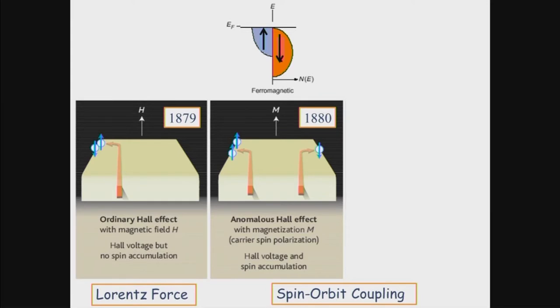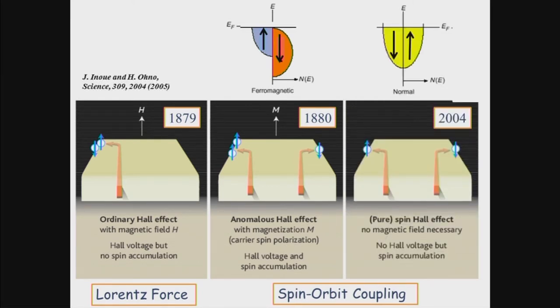And this is the anomalous Hall effect, not really useful as far as I know, but at least in the magnetism community or spintronics community, people believe the spin Hall effect might be useful. The spin Hall effect is for non-magnetic material, where you have equally populated spin up and spin down, and then you wouldn't get any charge accumulation locally. That's why it took us such a long time to realize this spin Hall effect. You have to use a non-local measurement.